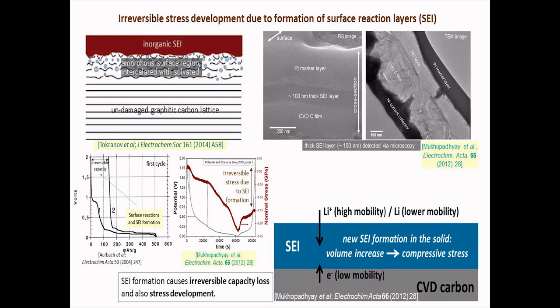And then, looking into it more closely, we realized that formation of this passivation layer is nothing but an electrochemical deposition of some film on the electrode material, which is now acting as a substrate, and these are known to lead to development of stresses both in the film and in the substrate. So this is nothing different from that.